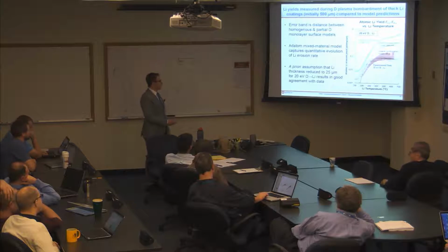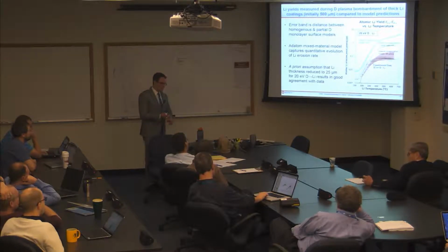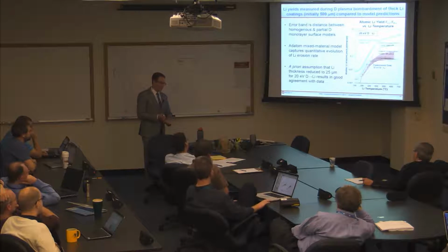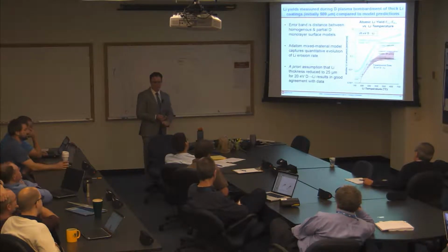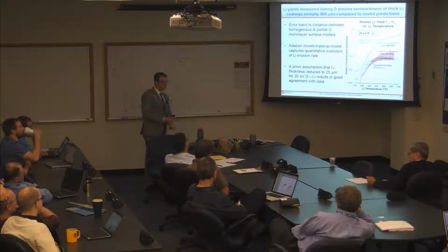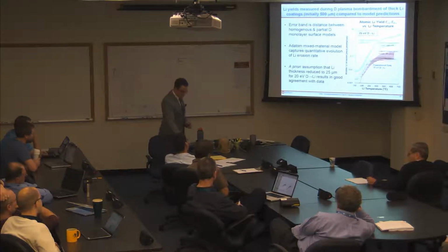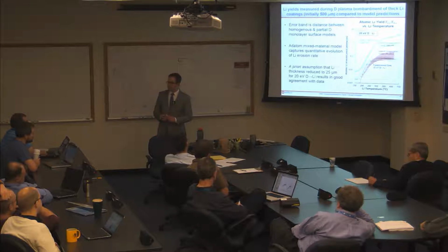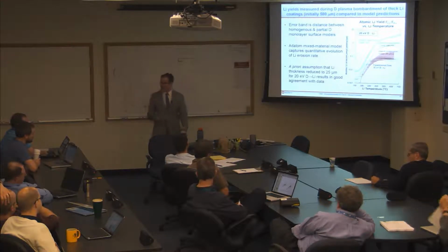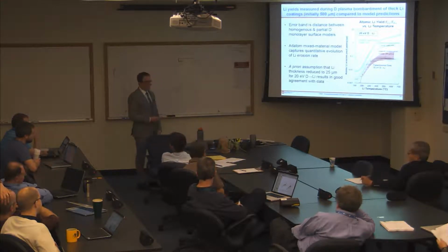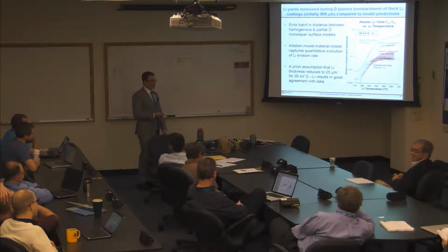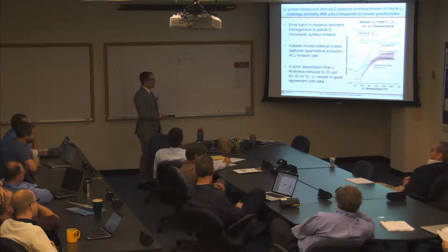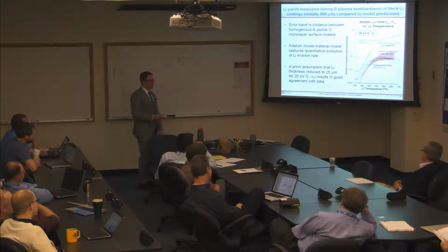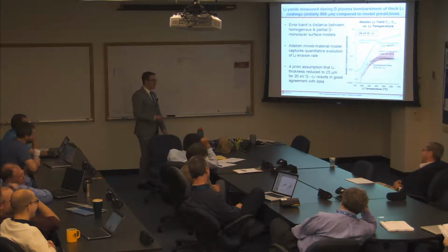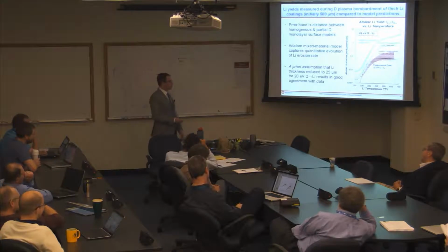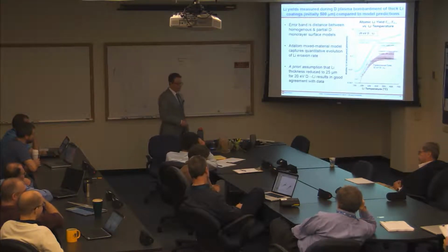And the error band here is the difference between the homogeneous lithium-lithium deuteride model and having a partial deuterium monolayer on the surface that I talked about during the theory section. That was about the thickness that you ended up measuring after the fact, right? Yes, it is, Matt. Thank you for pointing that out. During the confocal microscopy measurements, we measured anywhere from about 10 to 150. But if you average those, at least, it seemed to be on the order of 25, something like that.